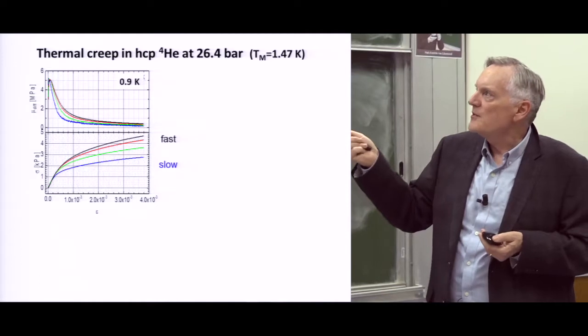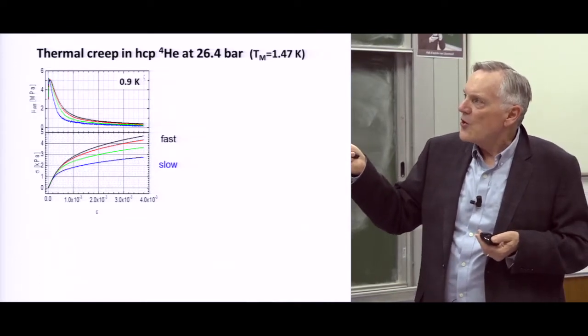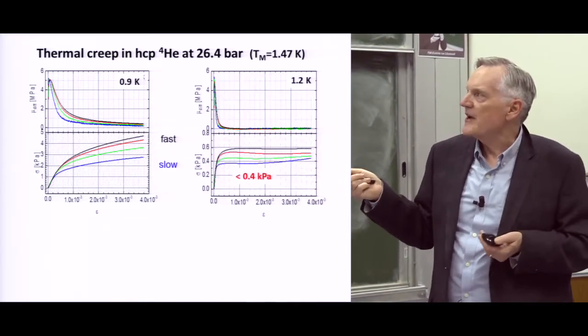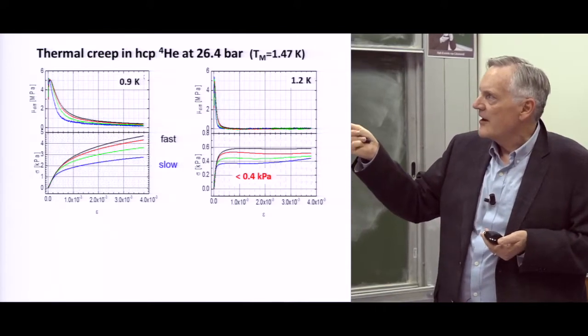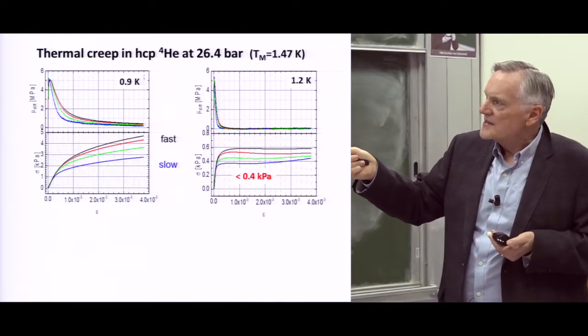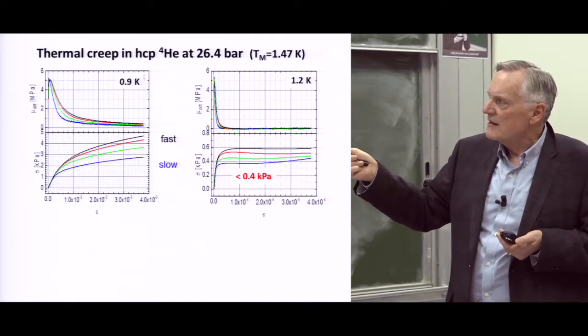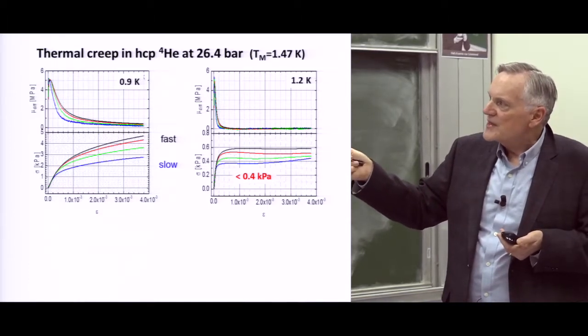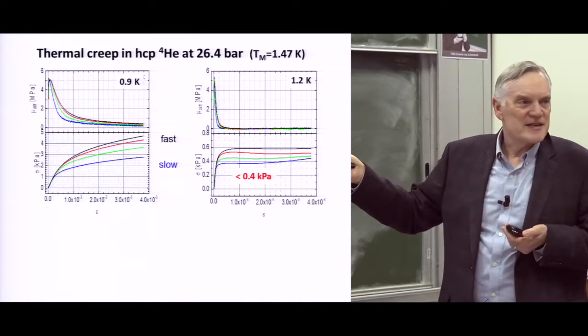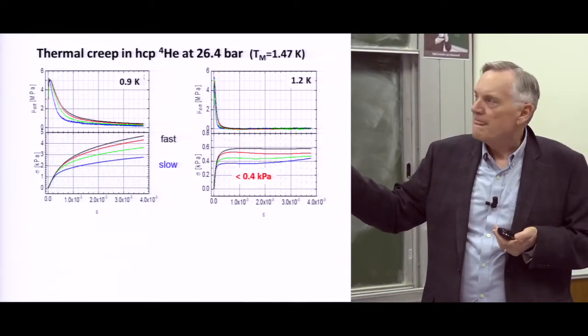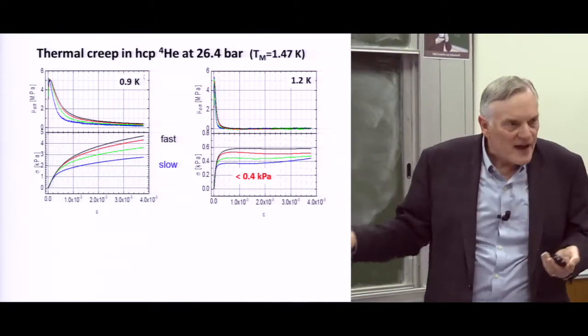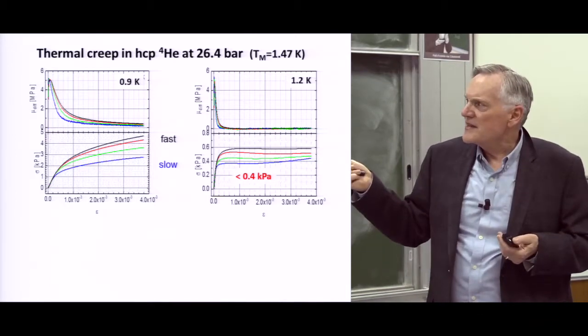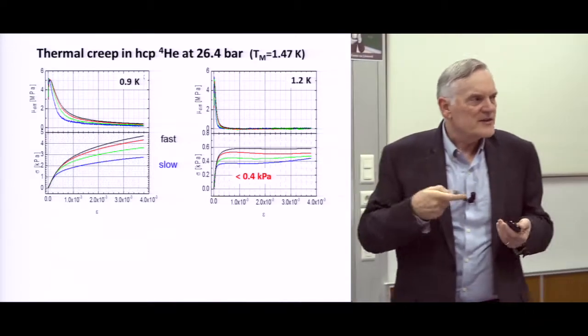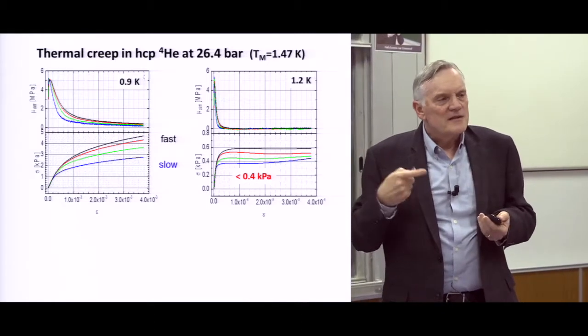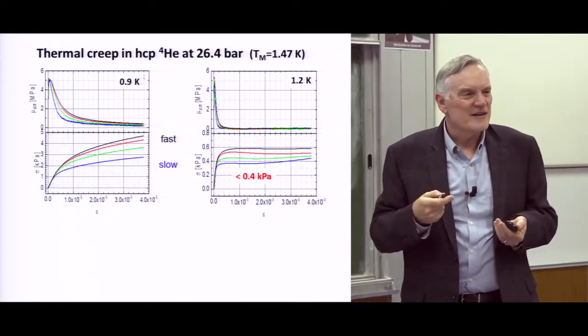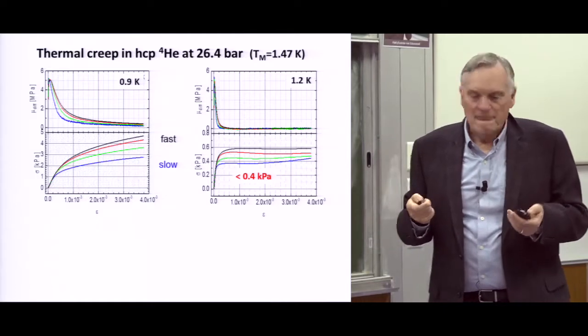If you go, this one melted about 1.5 Kelvin. If you go up to 1.2 Kelvin, everything's even faster. Same crystal, just higher temperature. And what you see now is it's even easier. Again, the fast one's a little harder to move, but as soon as you exceed about, it's about 10 times easier. The stress is here about 10 times smaller. And if I went closer to melting, there'd be another factor of 10 or 100 times. What that means is this helium, even though it's a crystal, it's a crystalline material, it's flowing at stresses that are really small.